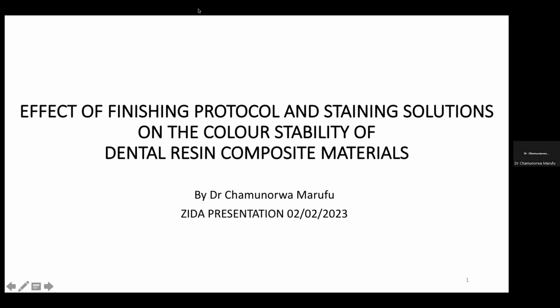And just to add on that, maybe something which you might also want to consider looking at, dentists sometimes when they do anterior composite, they have a tendency of placing bond, maybe you're using a plastic instrument and then you dip it in some bond and then you apply it on top of the composite to be able to nicely adapt the composite. Remember, the bond contains similar resins, of which there's a possibility that in so doing, actually altering the resin component of that surface area. This is just something I'm noting from speculation, not something which I have seen a study looking at, but potentially it's something which you should be cautious of when you are doing these anterior restorations, as it might increase the resin component and increase the chances of discoloration of the restoration. Thank you.